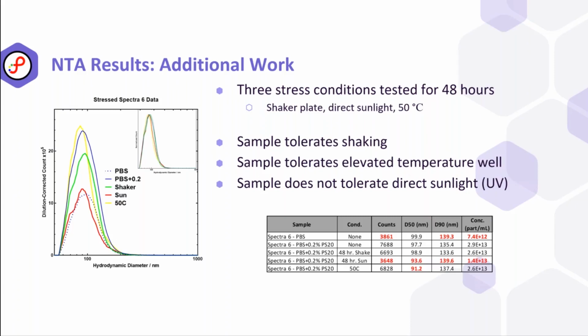And then what we do note is that this does not tolerate direct sunlight at all. So this sample is not stable under UV irradiation, and that's something that would typically be done during a stability panel for the product. So we see a huge drop in concentration. We see some major changes to the band shape and the particle size as well.